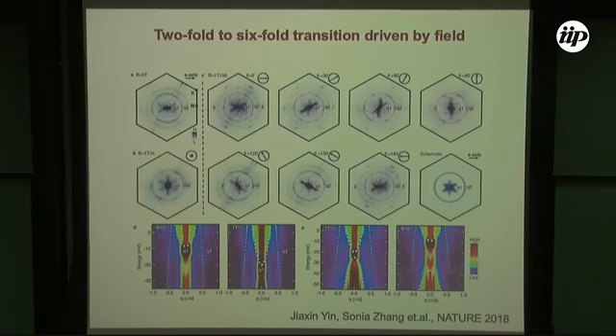But not only that, what is new here, unprecedented, is that in this case, we can control the nematic order direction. This is without any field, B equals 0. Here, when we apply a field in a certain direction, we can see that we are controlling the nematic axis. That is unprecedented. No other correlated system we know of where you can control the nematic order direction with a modest field, or any field. And then when you apply a strong out-of-plane field, your 6-fold symmetry recovers. So there's some sort of phase transition happening into this correlated state. And not only that, you can also reverse the direction.